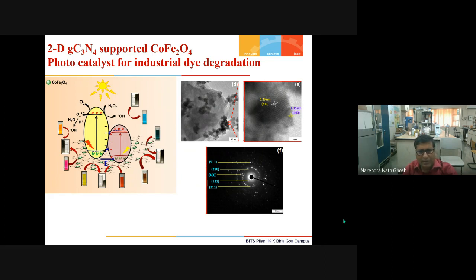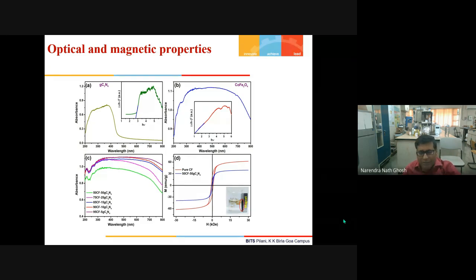Next, please. Now, as we are aiming for the photocatalyst, we have done the UV-DRS study of this material, first with the pure graphitic carbon nitride and pure cobalt ferrite, using the Tauc plot. We have determined their band gap. Also, we have done the UV absorption study for all the different compositions, and we have seen that the composites absorb far better than the individual graphitic carbon nitride or cobalt ferrite.